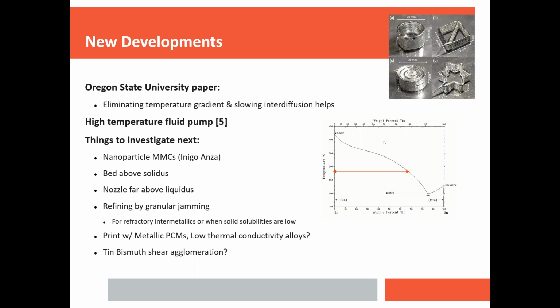The other thing that's interesting is if you have a very rarefied but still oxidizing atmosphere, because then sometimes the surface characteristics of the oxides on the metal actually can help the printing process. For example, in bridging and in producing wires from these materials, it may be beneficial to have the surface oxidation in order to help prevent the Plateau-Rayleigh instability. Anyways, I'm perfectly happy to talk to anyone after the talk as well, if they're interested.